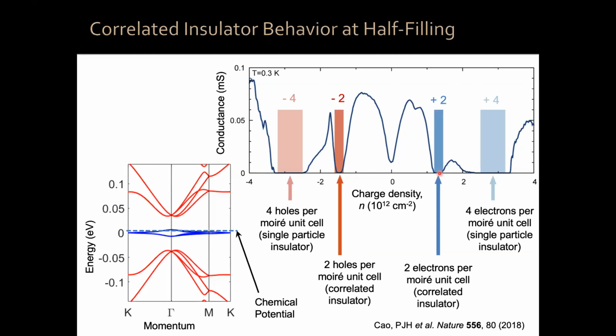The system should be a metal when we put these numbers of electrons or holes, and it's not, it is an insulator, okay? And this behavior, interestingly, is only observed when the angle between these two graphene sheets is very close to this magic angle. Only in a small angular range between about 1 degree and 1.2 degrees does this behavior happen. You can say that the magic only happens roughly between 1 and 1.2 degrees, okay?